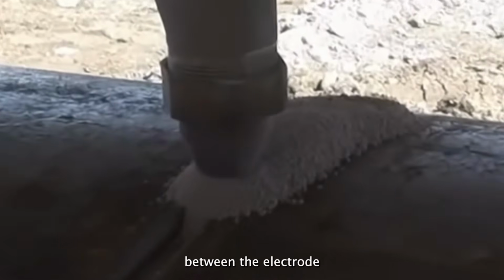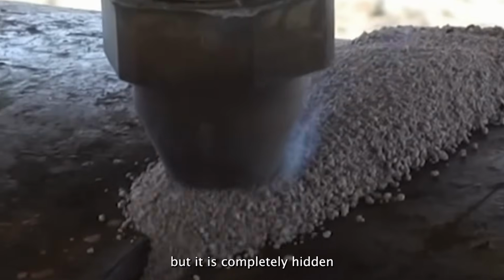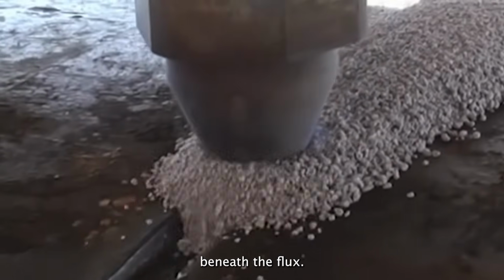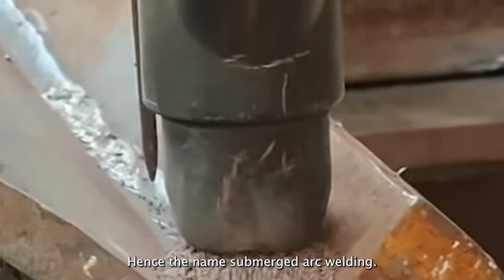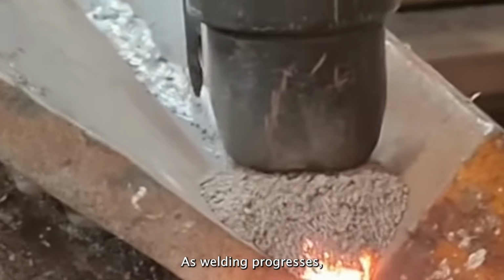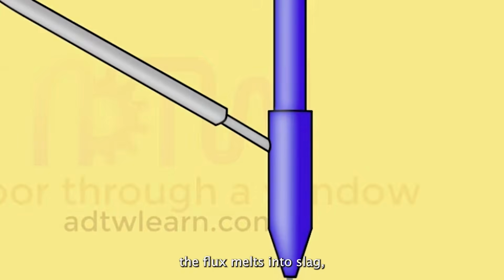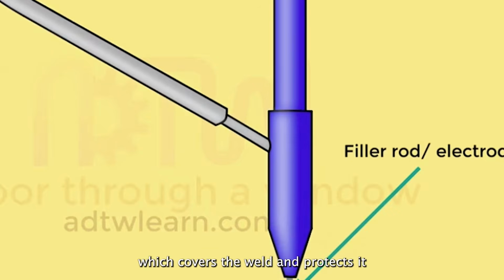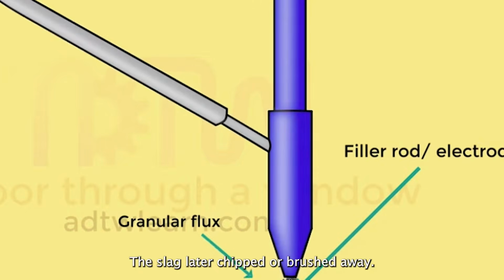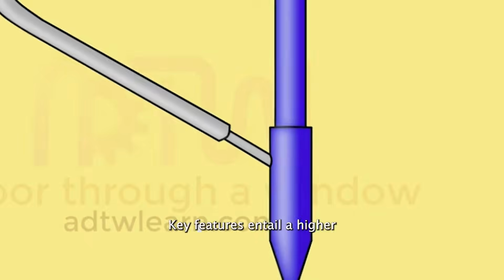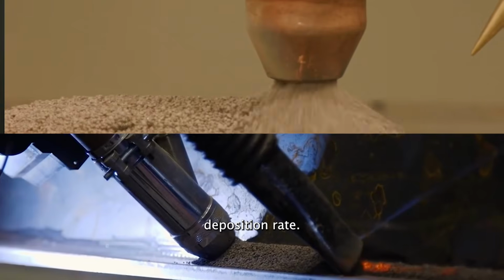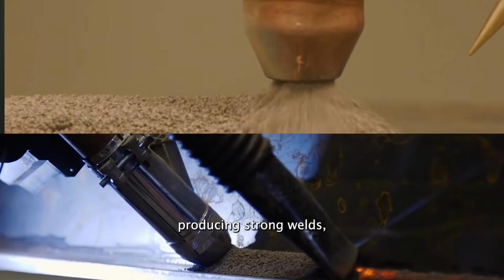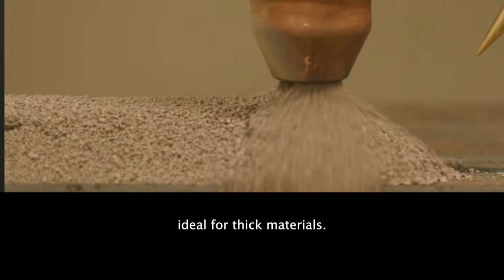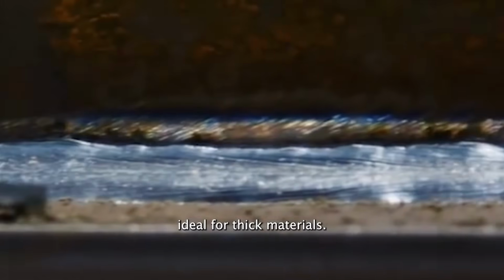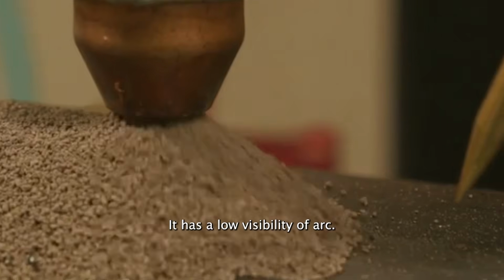The arc forms between the electrode and the base material, but it is completely hidden beneath the flux. Hence the name submerged arc welding. As welding progresses, the flux melts into slag, which covers the weld and protects it as it cools. The slag is later chipped or brushed away. Key features entail a high deposition rate and deep penetration producing strong welds, ideal for thick materials. It has a low visibility of arc.